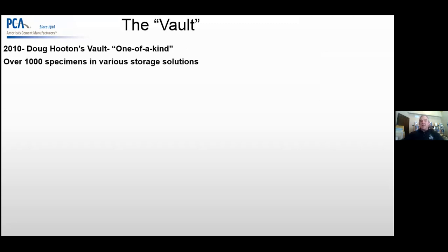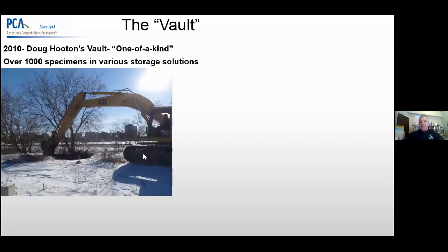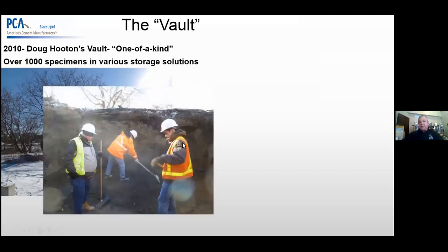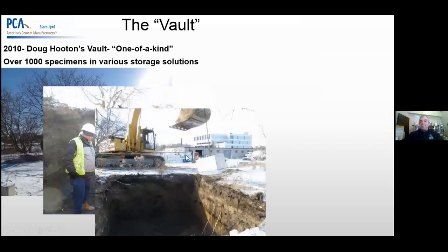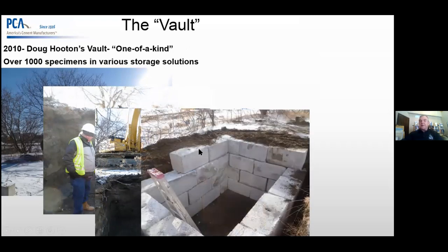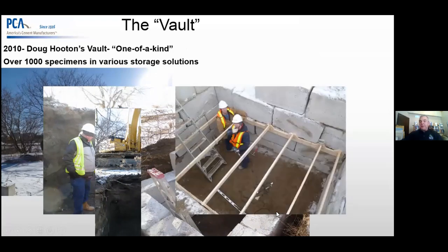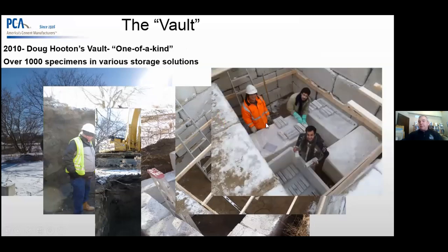One of the things that we did, Professor Hooton at the University of Toronto proposed a field site, and we offered up the field site to them. So we brought in an excavator, that's Doug on the left here with a couple of his students after the hole was dug. And we lined it with blocks. That's the Toronto office in the background. They gave us a little piece of land here right by the railroad tracks. So real nice of them. But anyhow, we made it work. We put some framework in there to make sure that the material was going to be protected from above. And then Doug and his students ended up putting over 1,000 specimens into this storage field site, the vault, as we call it.